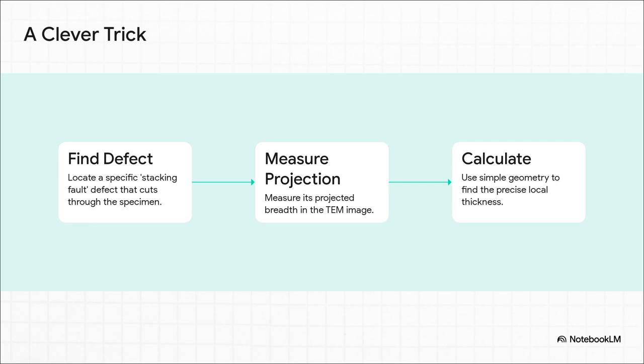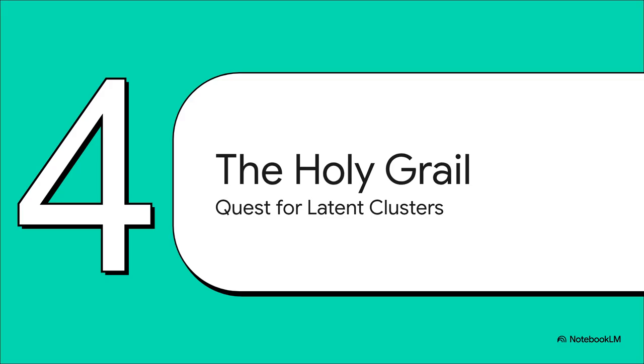Okay, so what they do is they find this specific kind of defect called a stacking fault. It's basically a flat plane that slices through the crystal at a perfect known angle. By using the microscope to measure the length of its shadow as it passes from the top of the sample to the bottom, they can use super simple geometry, like high school trig, to calculate the exact thickness of the sample at that precise spot. It's literally like using a crack in a window to figure out exactly how thick the glass is. Just genius.